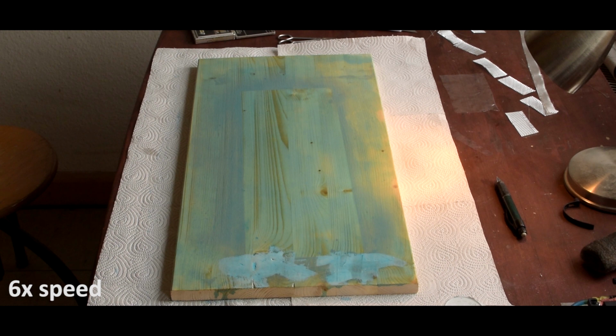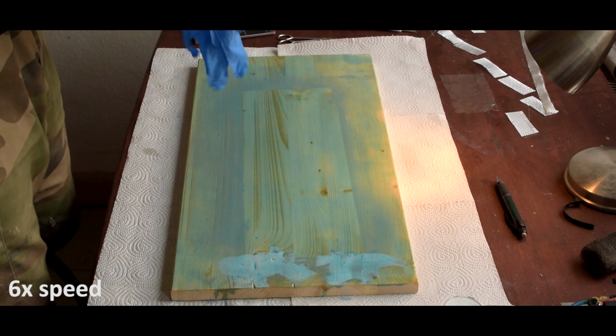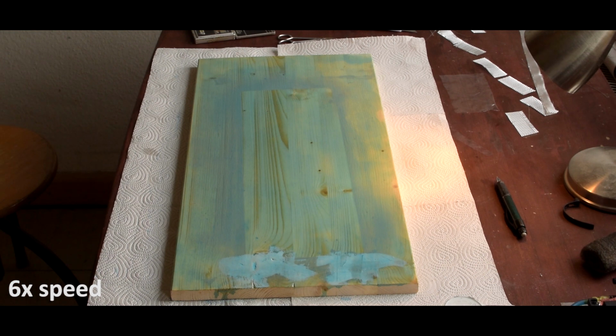This piece of wood is the underlay for the mold. It's important that it's absolutely flat. I covered the top with several layers of PVA mold release agent. You can apply PVA with a brush and it creates a thin, foil-like layer on top of the wood, so it's easy to separate the finished part from the underlay. Since the stuff is kind of toxic, always make sure to wear gloves when working with epoxy resins.